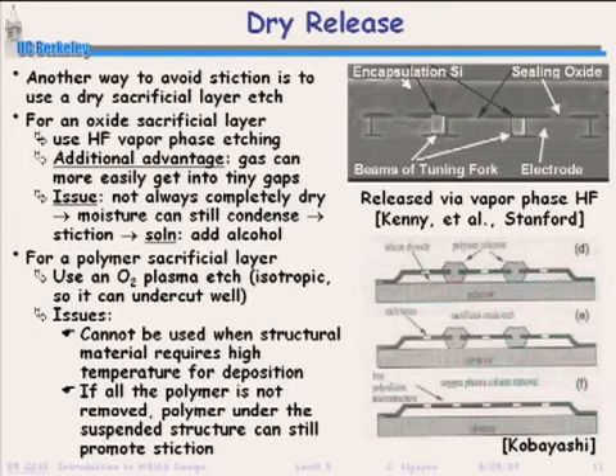One of them is vapor phase HF. So vapor phase HF, right, is where HF is not in a liquid format. It's a gas, and you're flowing this gas through your structures, and it's etching the oxide there and not attacking the silicon or whatever you made your structure out of. It's advantageous because it's a gas, right? The gas can get through tiny gaps, but the issue is that it's not always completely dry, okay? Moisture can still condense from this reaction, and if that happens, then you can still get sticking even though you have a vapor phase HF system.